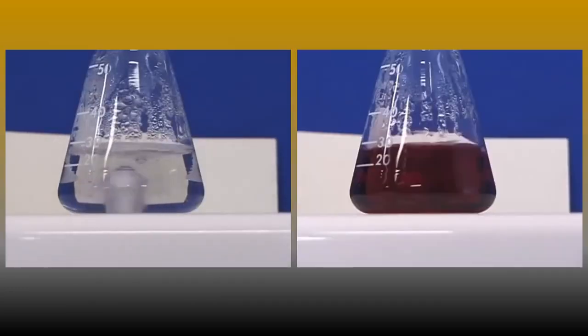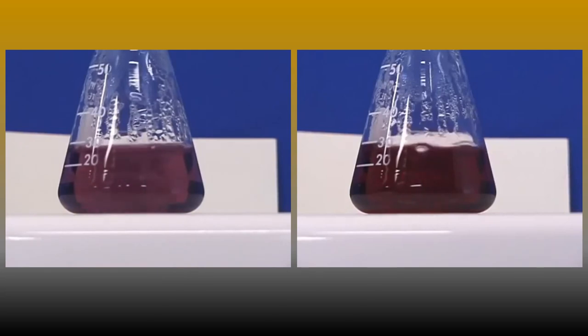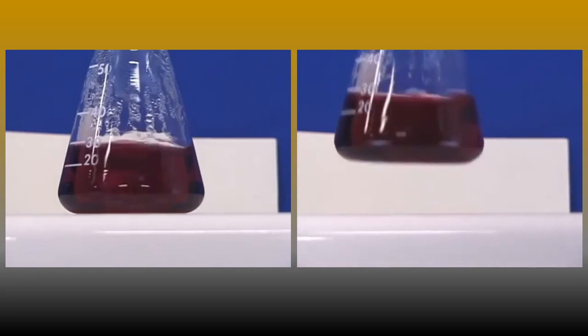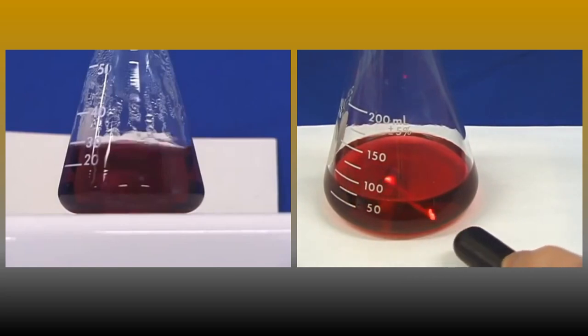In synthesizing gold nanoparticles, a common approach is to make colloidal gold by citrate synthesis. Colloidal gold is made up of gold nanoparticles suspended in solution. This process involves using a magnetic stir bar and hot plate to stir the solution until it boils. Then, sodium citrate is added, creating uniformly sized particles. The color will change to red to indicate the presence of gold nanoparticles of about 10 to 20 nanometers in size. The color of the solution is size dependent.